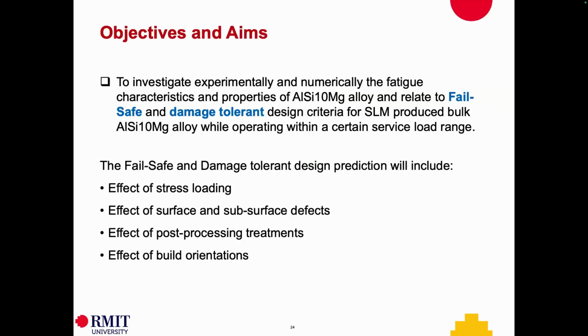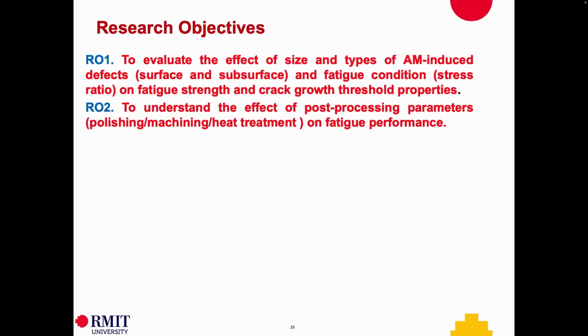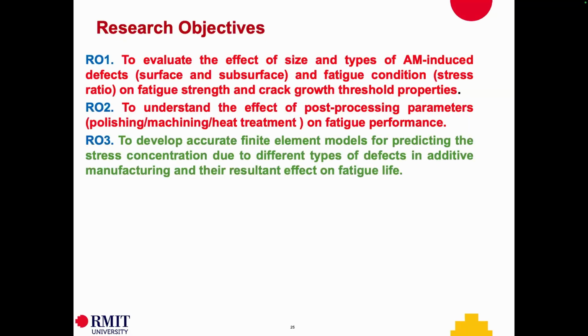Secondly, our main objective, why we summarize here: we were looking at the printing direction we talked about, but the key parameters are stress loading, surface and subsurface defects, post-processing, and build orientation. And our whole goal is to understand the effect of size and types of AM-induced defects, such as surface and subsurface defects, and fatigue conditions, such as stress ratio, on the fatigue strength and crack growth threshold properties. This is an important factor.